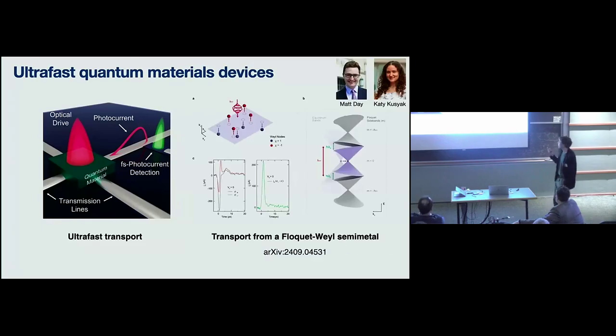And so one thing we've done recently in this kind of geometry is we've looked at transport from what's called a Floquet Weyl semimetal. If you take a Weyl semimetal or a Dirac semimetal, you shine circularly polarized light, you create these Floquet states. And in the photon-dressed Floquet band structure that forms, the Weyl nodes move. And so you can push these Weyl nodes around the Brillouin zone by controlling these Floquet states with your light. So this is not what I'm going to be talking about today.